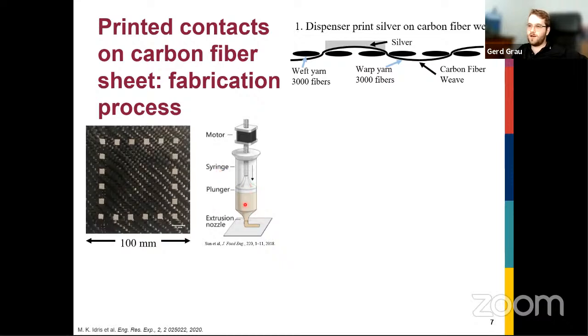So basically you have a nozzle, you have a high viscosity paste, you extrude it through this nozzle, and then you translate your nozzle relative to your substrate to generate whatever pattern you want. So we use this because it has a high viscosity. That means the ink doesn't get absorbed into the textile. It doesn't spread uncontrollably over the textile, which could be the case with inkjet, for example.